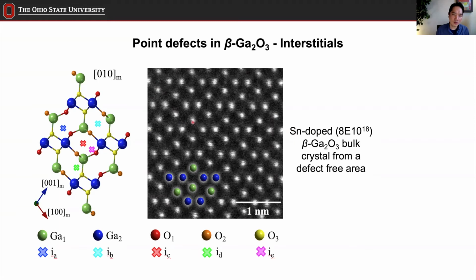Again, these are all gallium atom positions, but we have to define those positions first to make it easier for everyone to understand, because this is a very anisotropic structure. It is not like a regular face-centered cubic. This is a monoclinic structure that is very anisotropic. So there are two different gallium positions. One is the green one here, which is tetrahedrally coordinated, meaning that there are 4 oxygens nearby. And there's another type, the gallium 2 site, the blue one, which is octahedrally coordinated, which means that there are 6 oxygens nearby. So there are two gallium positions.